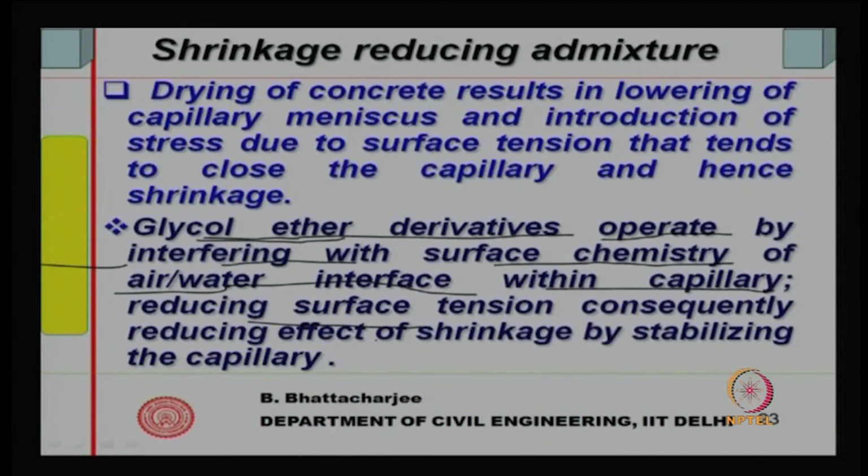Well, if you look at it, an air entraining agent also reduces the surface tension, but it has a head and tail, one being hydrophobic and the other hydrophilic. The hydrophobic side traps the air bubble, but here this will not happen.